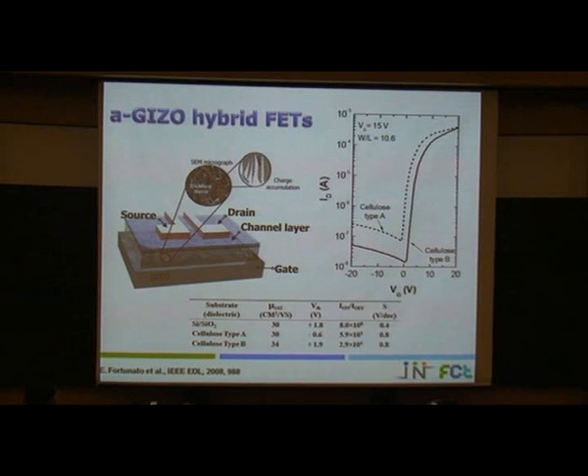This is the transfer characteristics, and also with a very high value of mobility. Of course, this is a comparison between these two TFTs, two hybrid FETs, and a standard one, the reference one. What is substantially different is the on-off ratio, because here we have some leakage. The paper, of course, is insulating, but we have some leaks, and the on-off ratio is not so high, it's around 10 to the third and 10 to the 4.